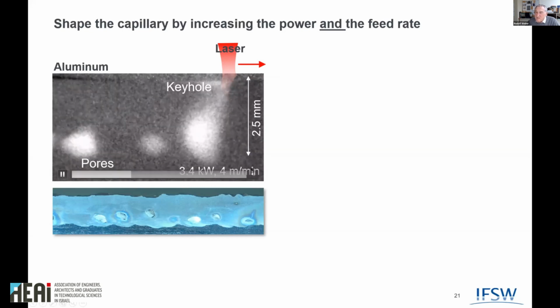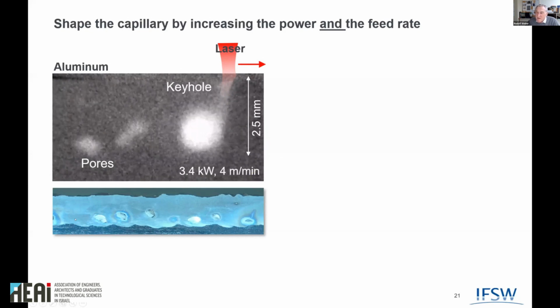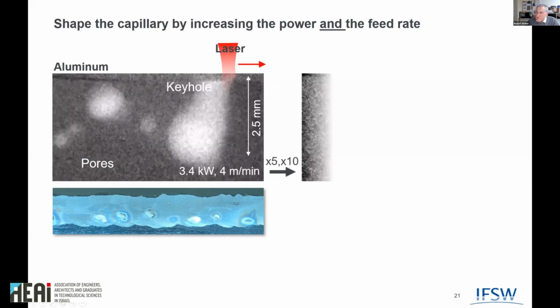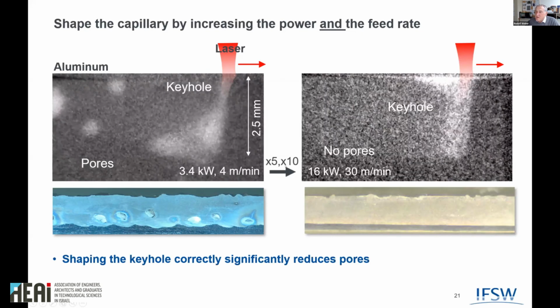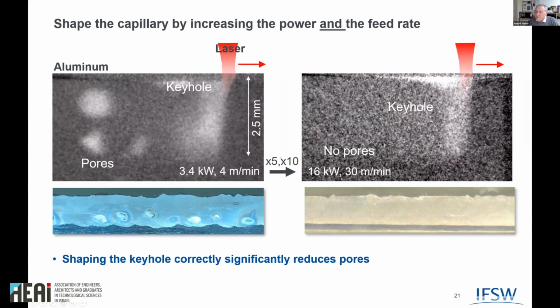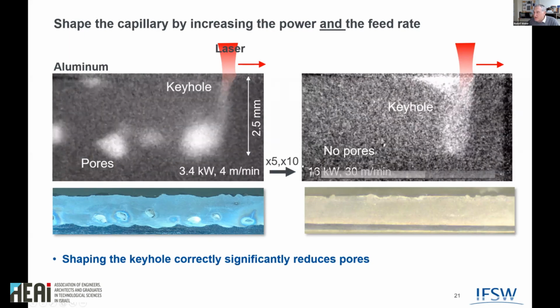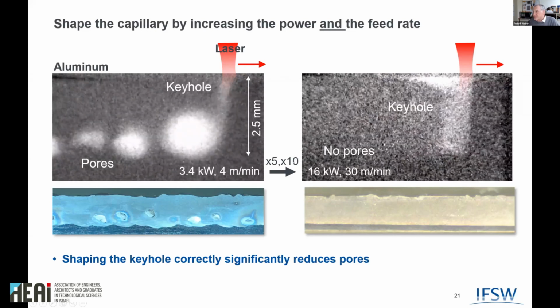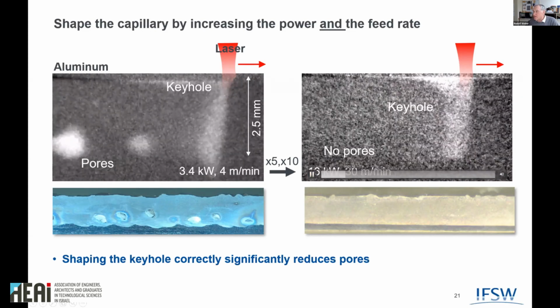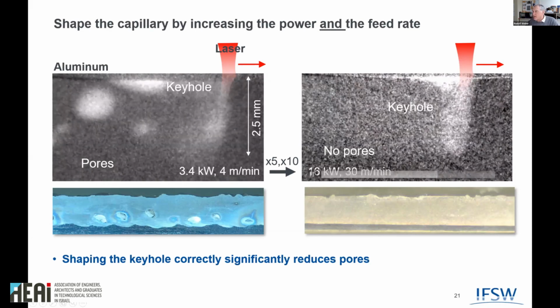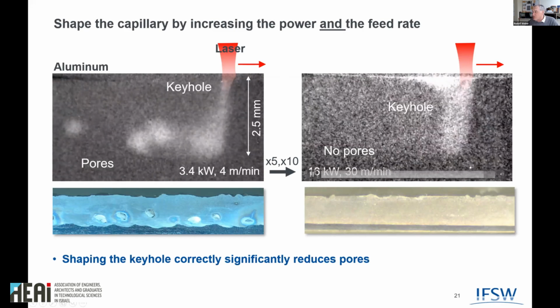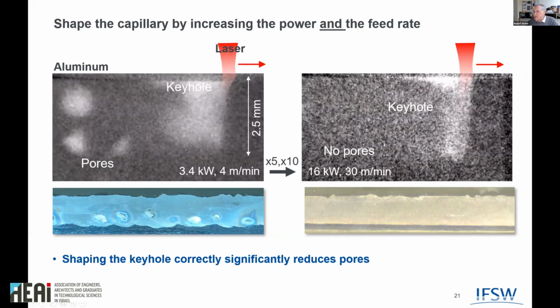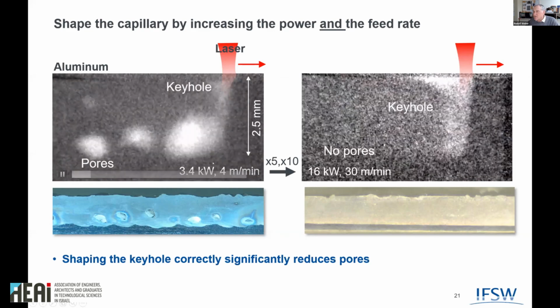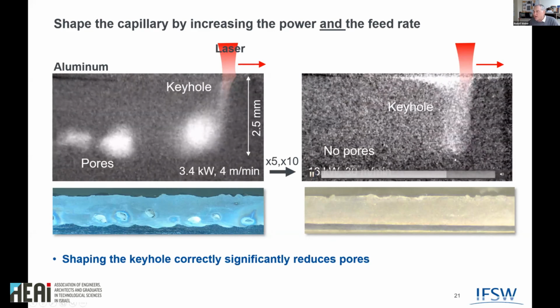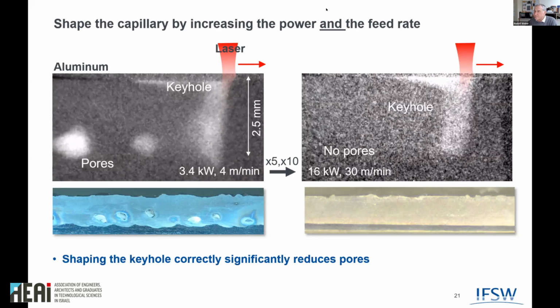This is also an answer to another question. A few kilowatts for a few meters per minute, and then you get these ugly welds. What you need to do is increase the power by a factor of 5 and the feed by a factor of 10. So the efficiency is getting better. We went up to 16 kilowatts, 30 meters per minute, and then we had this weld. It's about the same welding depth. It's this nice capillary with U shape. Everything is more or less perfectly stable. So you see it's about a factor of 5 in power and about a factor of 10 in feed rate.